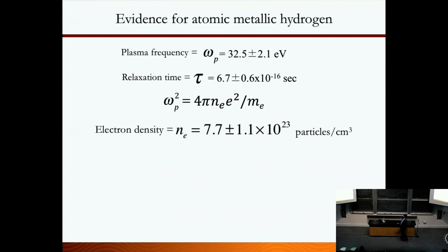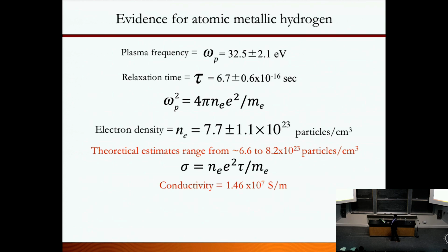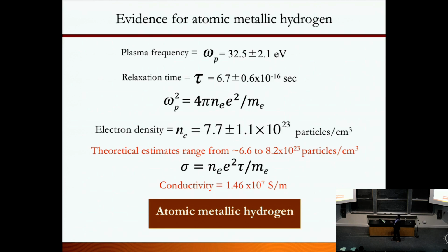It's roughly around 7.7, and the theoretical estimate is around 6.6 to 8.2, which is well within the theoretical estimation. And from there we calculate the conductivity is 1.46 × 10⁷ siemens per meter. It's very metallic. So we made the atomic metallic hydrogen. The density right here matches the atomic density if we go to the dissociative transition. So we have atomic metallic hydrogen.